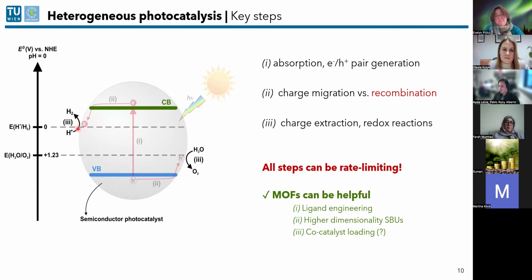However, of course, it would be better to move away from noble metals, and this is also something that we're interested in doing. So just go to some earth-abundant metals, for example, copper or nickel, cobalt as well. These are metals that also work for hydrogen evolution, although not as good as platinum. And this is why designing, for example, that was what I was saying about this co-catalyst design of the secondary building units. Mixed metal SBUs might be very useful here, because then, although the co-catalyst maybe doesn't work as good as platinum, if we have it very much dispersed throughout the particle, we could get similar. Like doping, right? Yeah, exactly. We could get better performances.